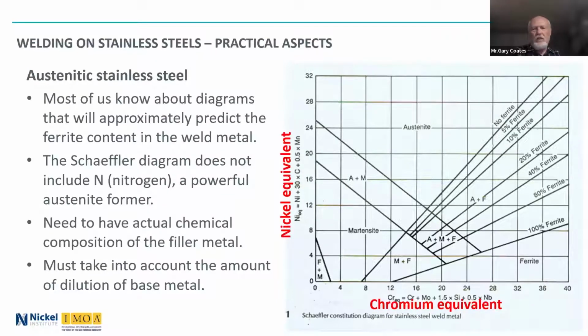But it is important to have, when you're using these diagrams, the actual chemical composition of the filler metal. I was actually shocked when I was younger that we got mill test certificates for the welding filler metal from a number of manufacturers, and they weren't actuals, they were typicals. And the typical is pretty useless. The electrode you get might be close to the nominal value, but it may be different from that. So you need to ensure, if you're using these diagrams, that you have the actual chemical composition of the filler metal. And you must take into account the amount of dilution of the base metal, because these diagrams are made for 100% weld metal, but in welding, you do get dilution from the base metal, and the base metal will generally have a very low ferrite content theoretically when you plot it out on these diagrams.